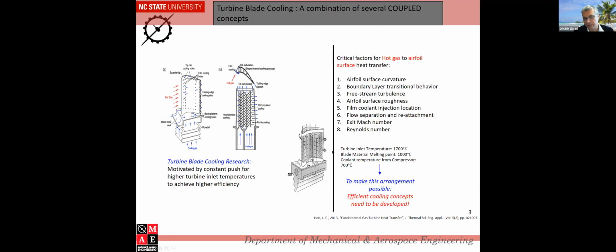So if you take this into account, the turbine inlet temperature is about 1700 degrees C. The blade material melting point currently is 1000 degrees C. If you add the TBC coating, then you can go up to 1200 C. And you have cooling air from the compressor that's coming in at 700 C. So basically, I have to use the 700 C air to make sure that the metal temperature comes down to 1000 degrees C while it is exposed to conditions of 1700 C.